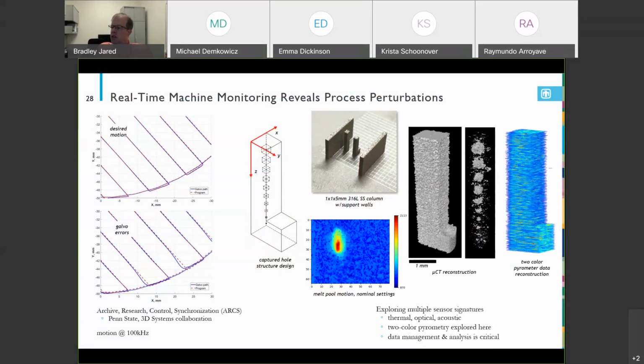Looking at real-time monitoring. On the left, there's an image tracking the galvo motion of the laser itself. And you see here in the bottom left, there's actually deviation. So this is what it's supposed to be doing, and we see a millimeter of travel variation. This was a test run, just checking some stuff with the galvos, and we saw this error, which was very unexpected, right? And so this could potentially be an impact for a defect.